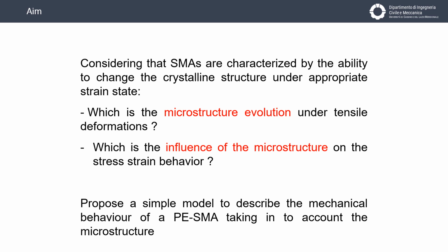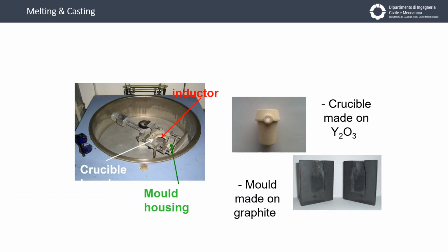In this work, we proposed a simple model able to describe the mechanical behavior of the shape memory alloy characterized by a pseudo-elastic effect, which takes into account the real microstructure of the material. In order to better describe the phenomena, we start from the experimental results. And the first step